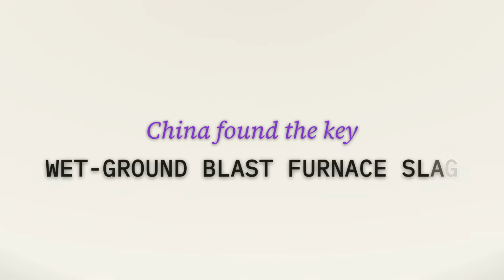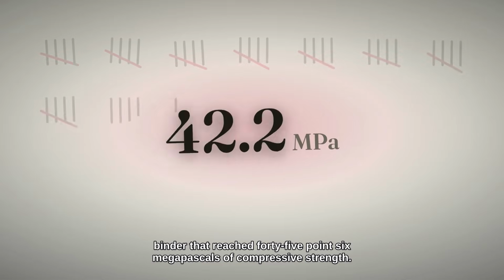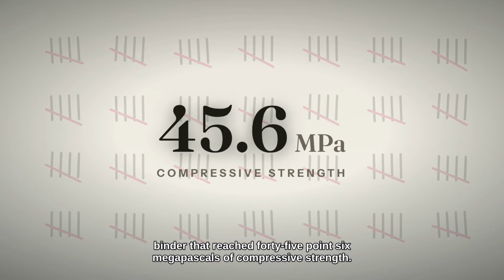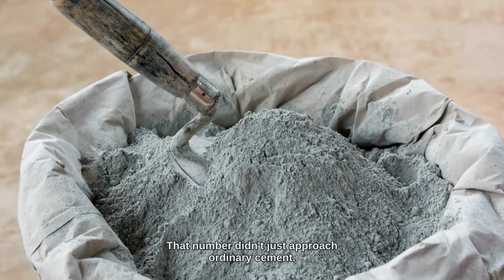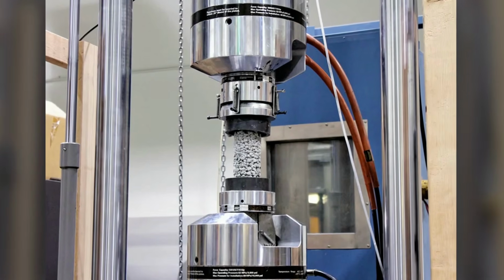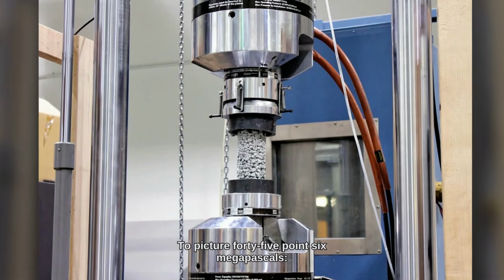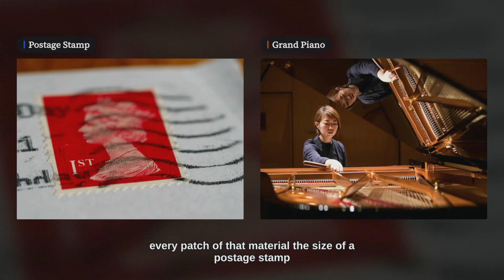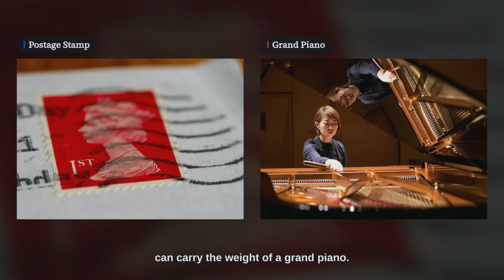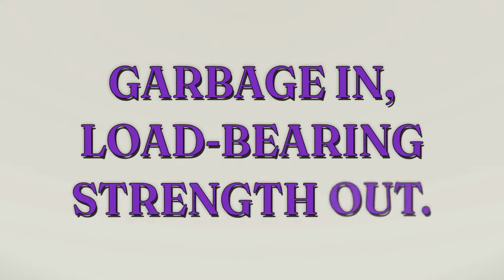A team took wet ground blast furnace slag, mixed it with phosphogypsum and carbide slag, 3 waste streams, 0 clinker, and produced a binder that reached 45.6 megapascals of compressive strength. That number didn't just approach ordinary cement. It exceeded it. To picture 45.6 megapascals, every patch of that material, the size of a postage stamp, can carry the weight of a grand piano. No kiln, no coal, no quarry. Garbage in, load-bearing strength out.